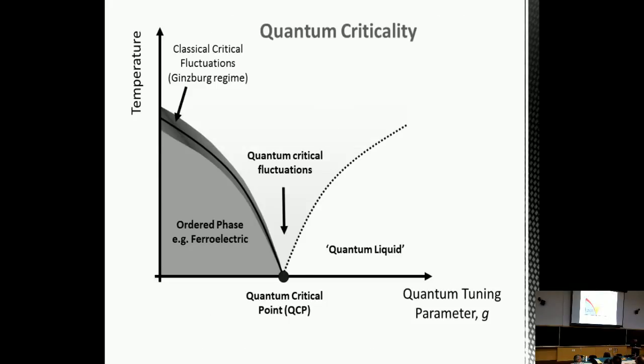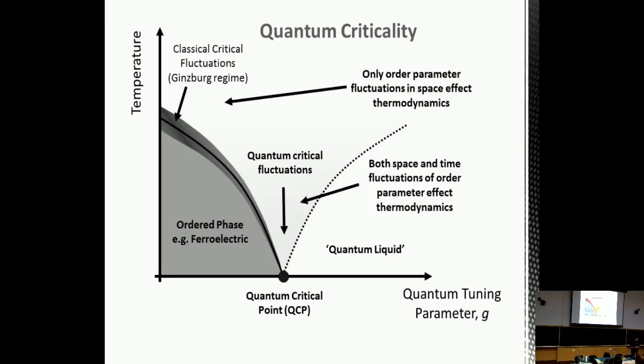So what's interesting about the quantum critical point is that there's a very large region here shaded in yellow, the quantum critical regime, which opens up when you suppress a transition to 0. And in this region of the phase diagram, you need both dynamics and spatial fluctuations of the order parameter field to understand the thermodynamic behavior. Whereas at a classical transition, it's just the spatial fluctuations of the order parameter that affect the thermodynamics. And the other interesting point is that close to the quantum phase transition, one often sees the emergence of new states of matter. And so it's interesting to ask what could happen in the case of the ferroelectric under those conditions.